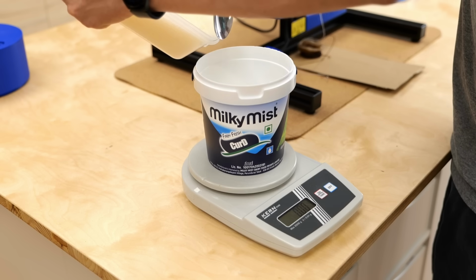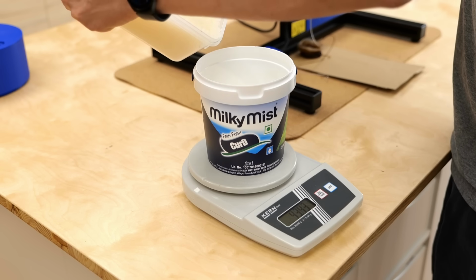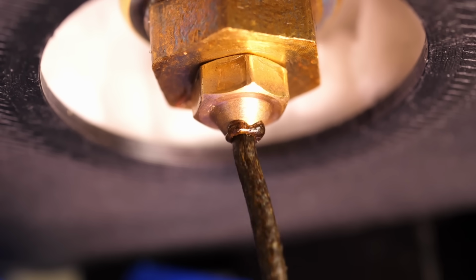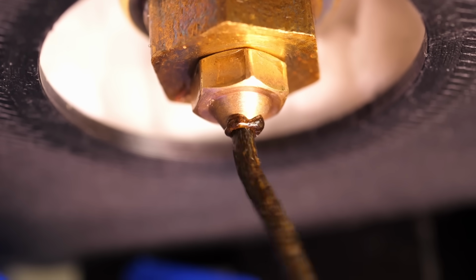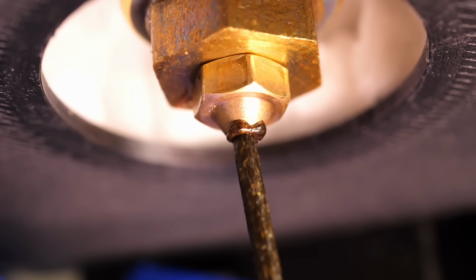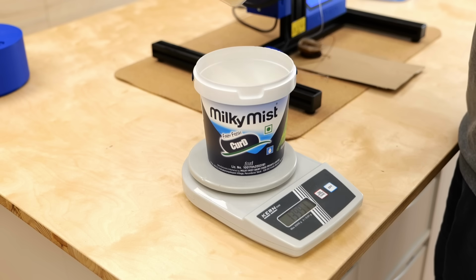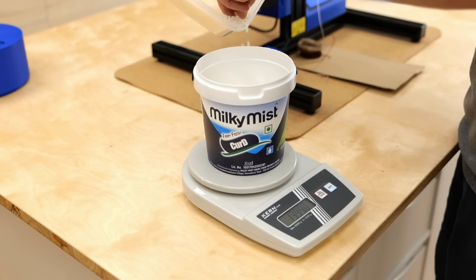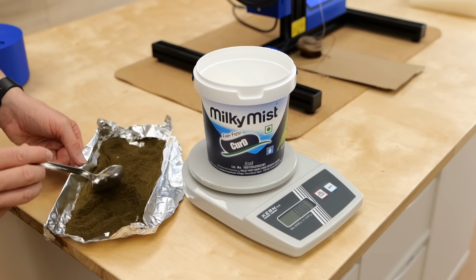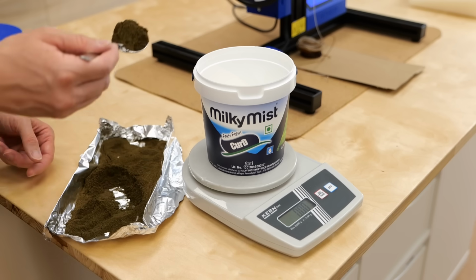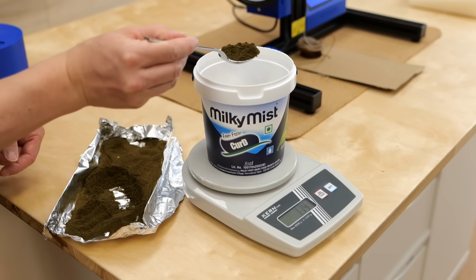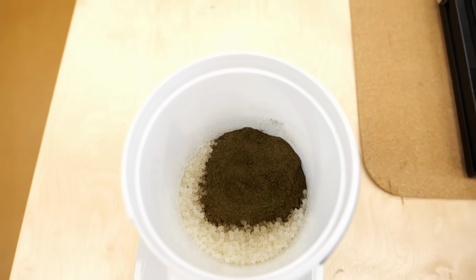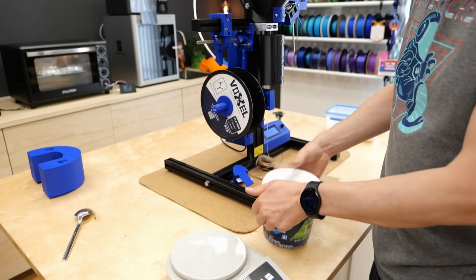I first added the PLA pellets, but how much poop should and can we even add? Even though it would be nice if we could replace a lot of the plastic, the more fibers we add, the more difficult extrusion and also printing will be. So for my tests, I thought it was a good idea to start with a low mixing ratio. I weighed 150 grams of freshly dried PLA pellets and added 7.5 grams, so 5% of our poop powder. In order to make sure that everything was evenly distributed, I closed the lid and mixed it all up.